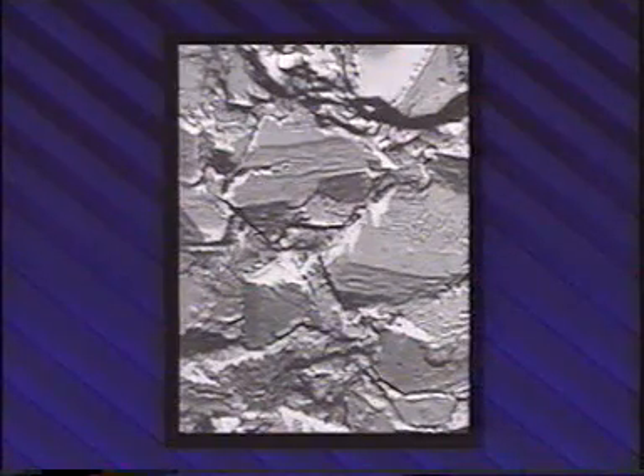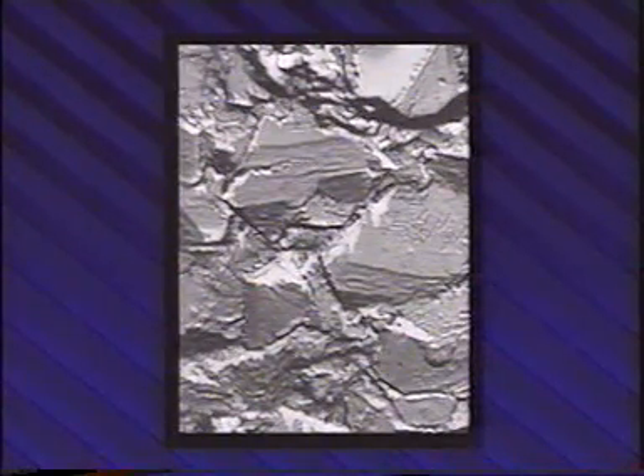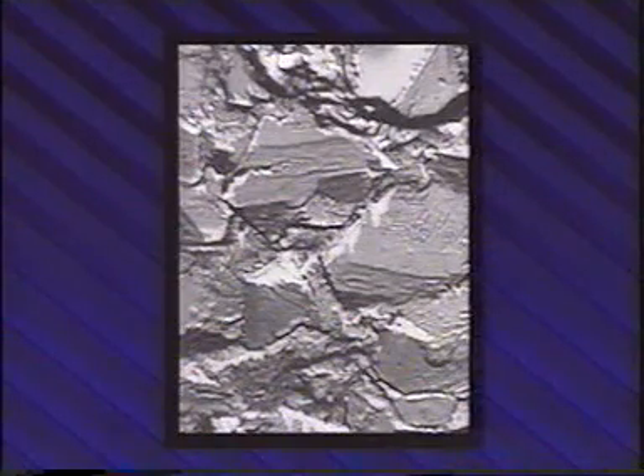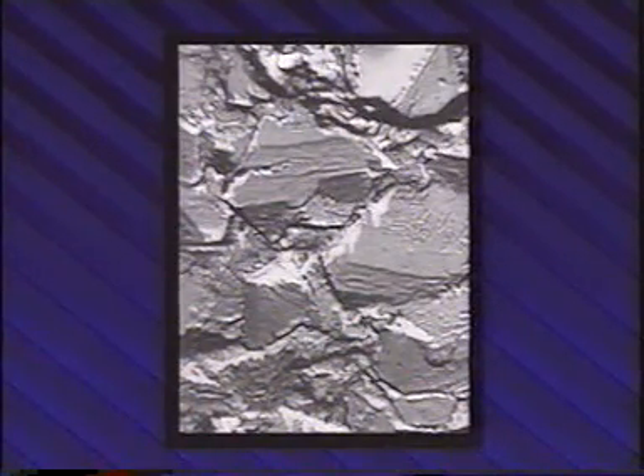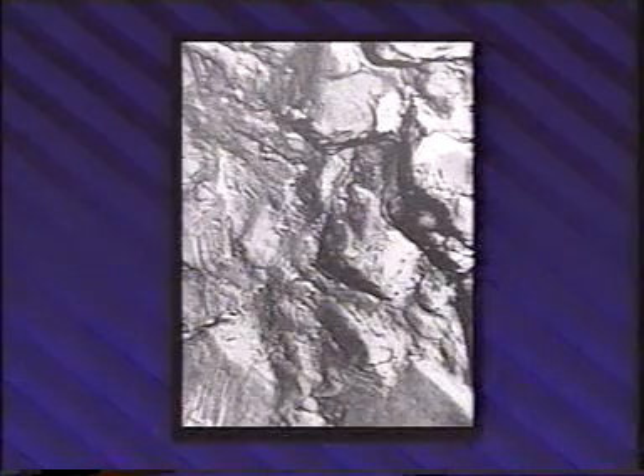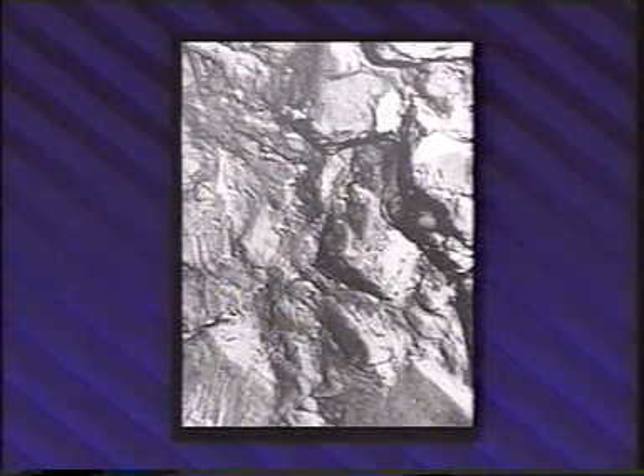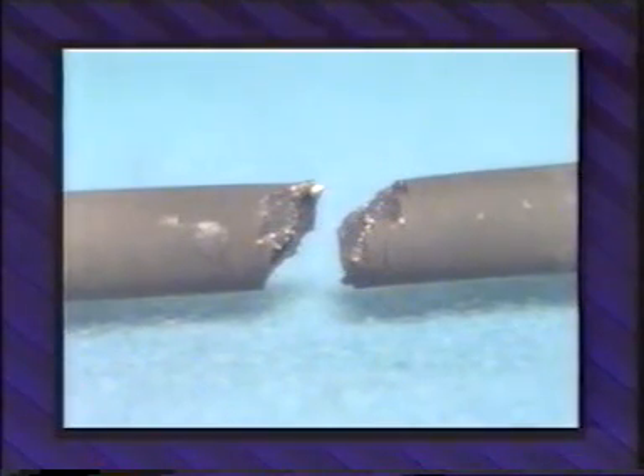Depending on the alloy, the fracture by stress rupture may appear macroscopically as either ductile or brittle. Ductile fractures are transgranular and are typically accompanied by more pronounced distortion. A brittle fracture is usually intergranular and occurs with very little distortion. Intergranular cracking may not be readily discernible on the surface of a brittle stress rupture fracture. If the oxide is removed, the mode of cracking will usually be visible.